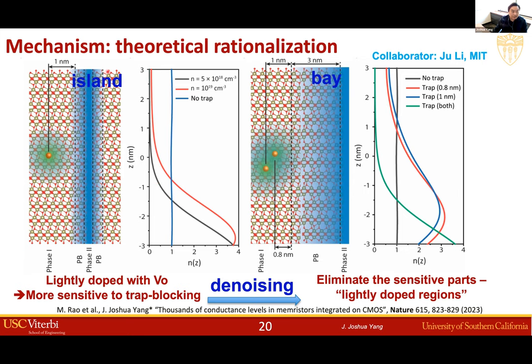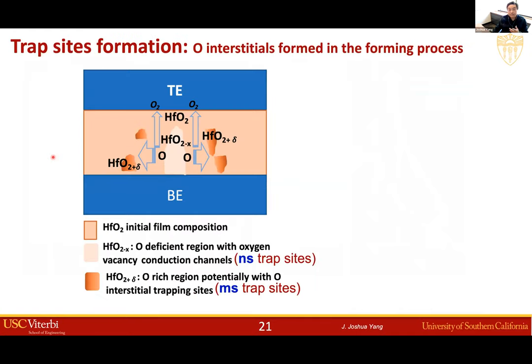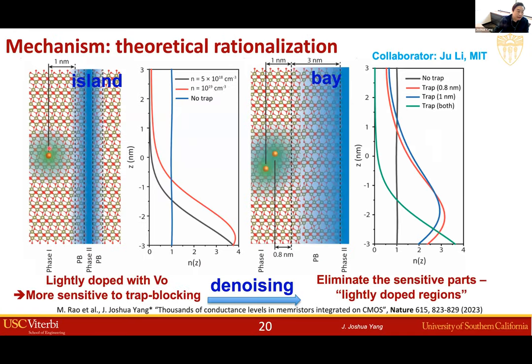So in order to remove such noise, naturally, we want to get rid of the incomplete channel. And you can get rid of the incomplete channel by completely removing it, by removing all the oxygen vacancies. So you can denoise it that way. You can also get rid of an incomplete channel by making it complete. In that way, you put more oxygen vacancies in it, so the channel is less sensitive to a trap nearby. So that's the denoise mechanism. But of course, another way to get rid of the noise is to get rid of the trap centers. It turned out to be harder to get rid of the trap centers.